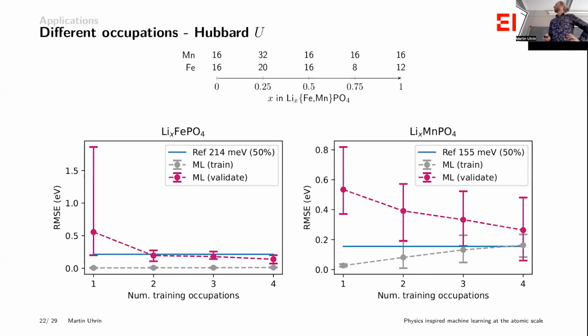Similar story for the manganese. Actually, I'm doing myself a disservice here because you can see the scale is only up to 0.8 here. So this looks worse than that, but actually it's much better. So we can actually already just take one of these and it will be able to predict the rest.